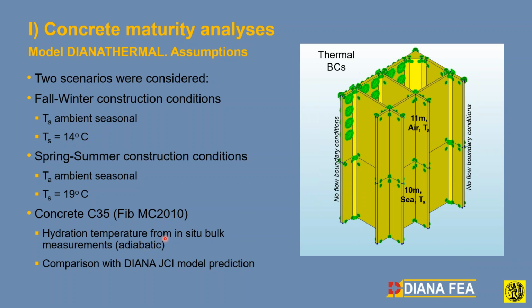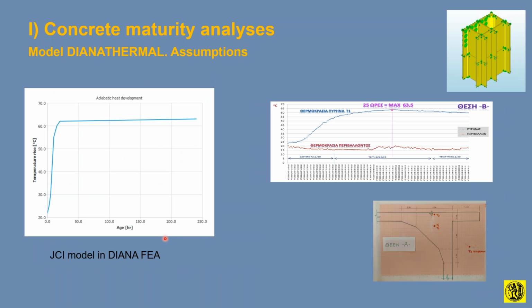The hydration data for the model, we took directly the hydration data that Diana gives for the particular concrete grade, the C35, which was the in situ measured quality of the concrete, for the adiabatic heat development using the Japan Concrete Institute. But we actually requested measurements from the contractor, and we saw that the in situ measurement near the massive footing, fairly deep, which is a fairly adiabatic condition, gave a temperature gain over a day and a half of the order of 62 degrees centigrade, which was very close actually to the same heat development curve that the Japan Concrete Institute gives for this specific concrete. So we kept it. And we did the analysis.